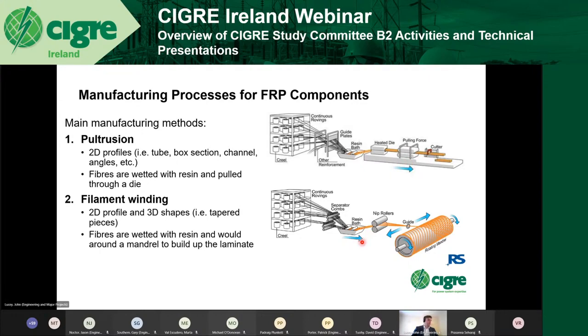Because you can taper them, you can stack them, you can modularize the poles themselves, and you can stack them on top of each other, where you can't really do that with pultrusion. They're all the same size. So typically for the pultrusion poles that are on the market, you'd get to about 18 or 19 meters max. Whereas the filament wound poles, you can go up to anything up to even 52 meters.